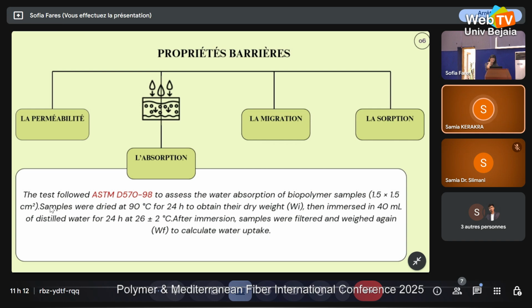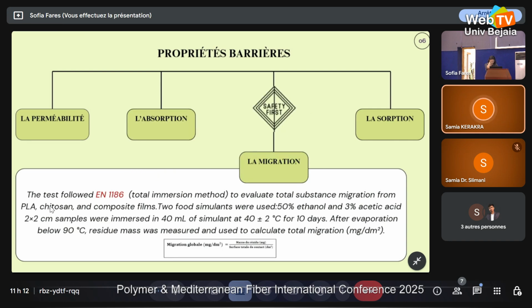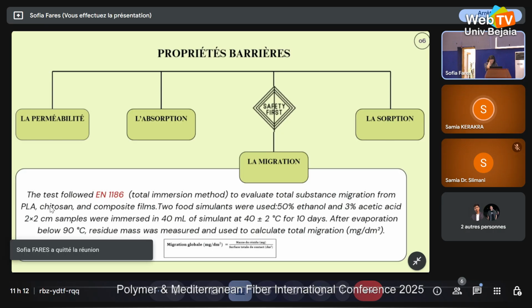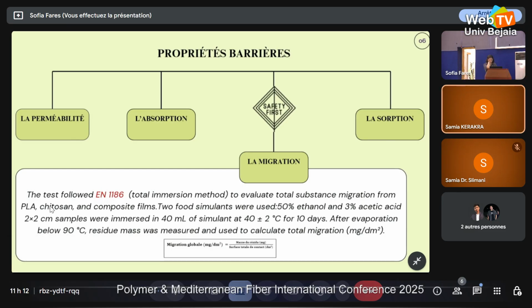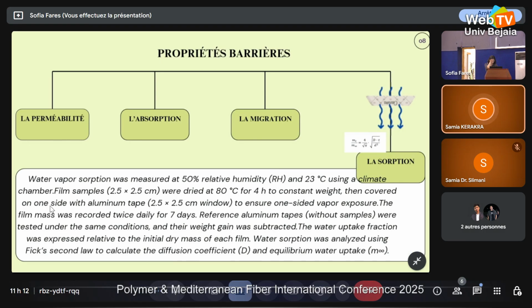And the third one, migration. The tests followed EN 1186 total immersion method to evaluate the total substance migration from PLA, chitosan, and composite films. Two food simulants were used. The first one is 50% ethanol, and the second one is 3% acetic acid. And the last one is sorption, where water vapor sorption was measured at 50% relative humidity and 23 degrees Celsius using a climate chamber. The test is explained in this slide.